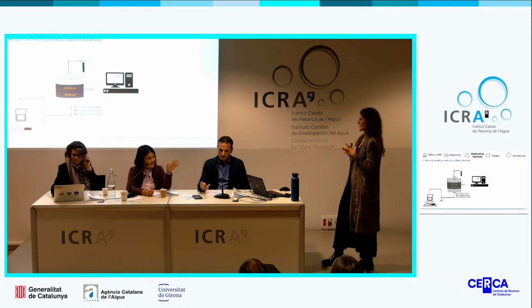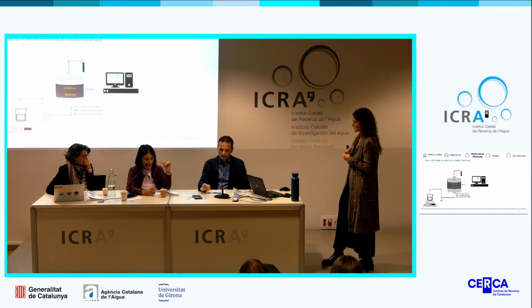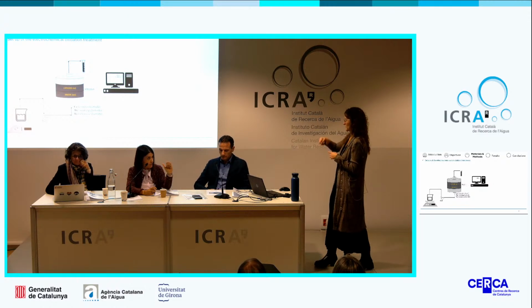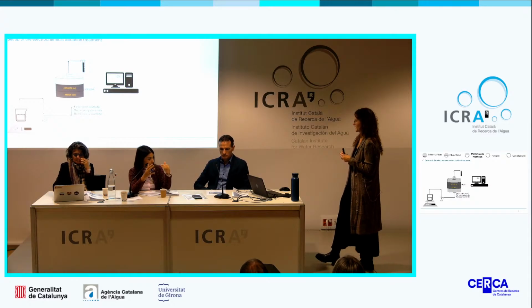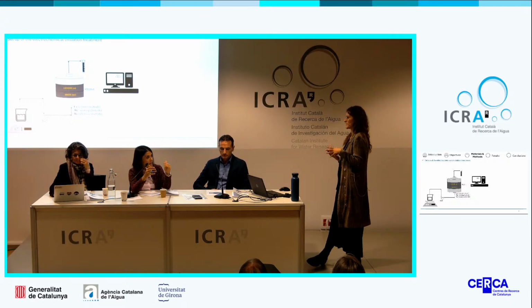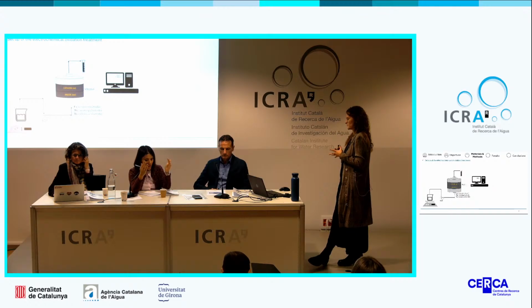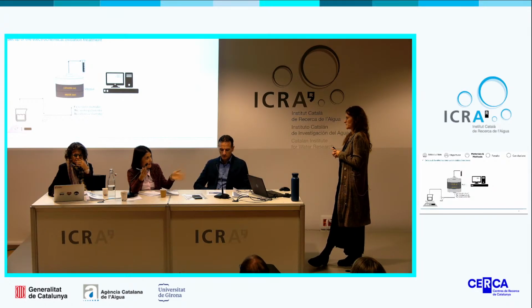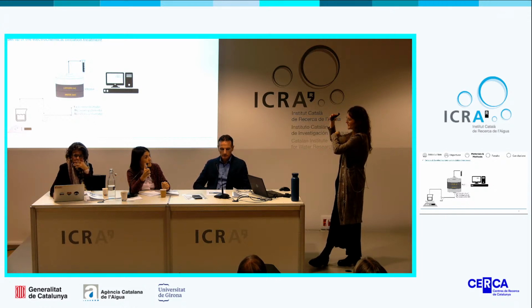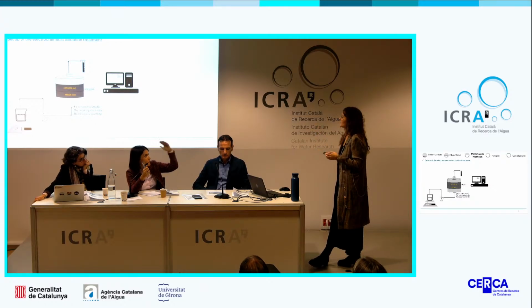In the case of using intermediate current, you said that the lower log removals may be explained by the retention of oxygen and hydrogen bubbles in the second reactor. But do you also stop the flow rate? No, you only stop the current. Yes, we stop the current. Because our materials have capacitance, even with the current switched off, they are still degrading. But why are oxygen and hydrogen bubbles retained in the second reactor if the water is flowing? Because we are producing bubbles, and bubbles can accumulate in the reactor, even though it's a flow-through, with water passing through the electrodes.